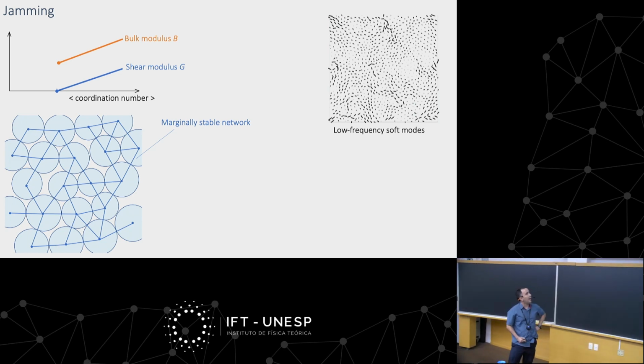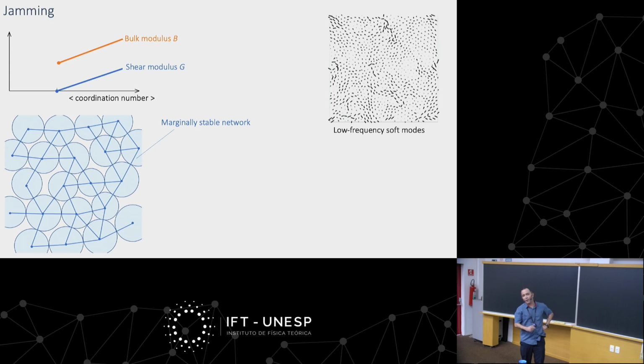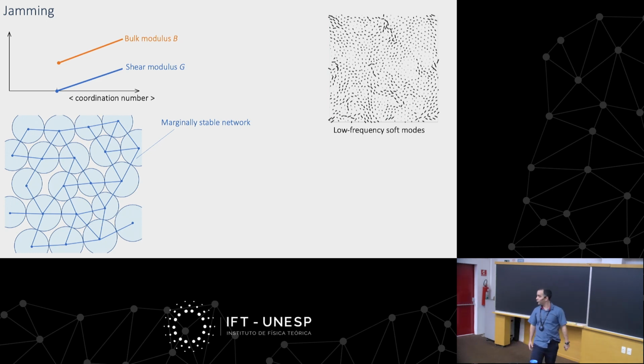One of them is that if you add a few more bonds, or if you compress the system a little further, you have this population of low energy excitations in the system. And here I'm giving one example of one of these low frequency soft modes. It's very hard to see here, but there are some dots representing the particles, and the lines are the polarization of the particles, so they want to move in this or that direction. So it's a kind of disordered low frequency soft mode. It costs very little energy. And this happens because you have a network that's marginally stable. It's just on the verge of being mechanically stable.